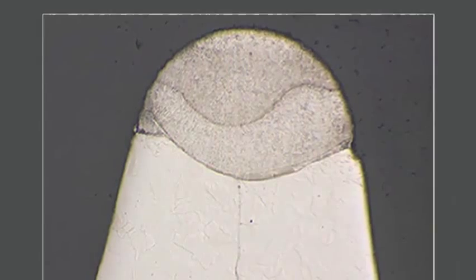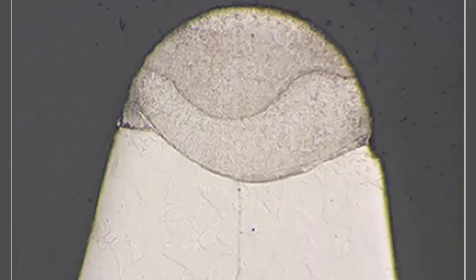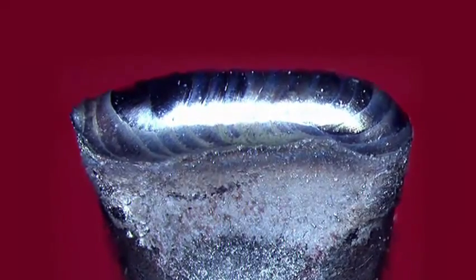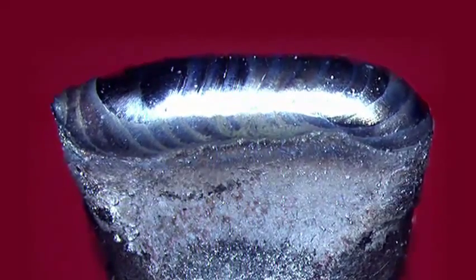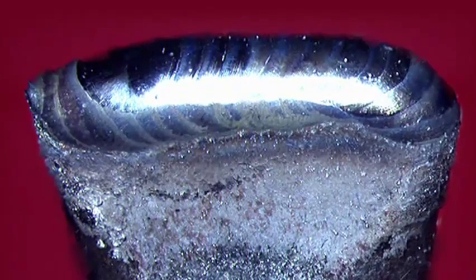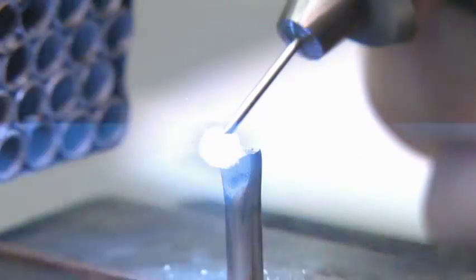The process that we developed was essentially using an alloying technique using the laser. By doing so, we're changing the structure of the inherent substrate material from an austenite to a ferrite phase during the resealing of the laser weld. We're able to do that by alloying with a material with a higher chromium content that can later be laser welded crack free.